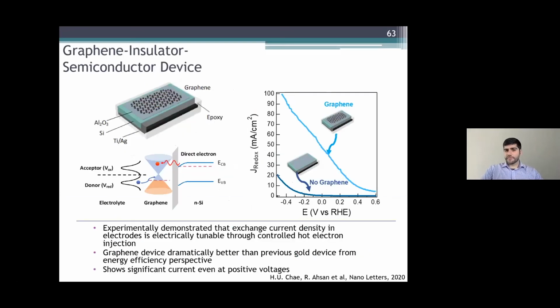And we also did this with graphene, and we found that we could again get these pretty nice shifts over to lower applied voltage for the hydrogen evolution reaction, and it was a little bit better than our gold devices. And something that was particularly interesting about the graphene is that we got a lot of modulated, what we call direct injection current, where essentially the silicon electrode was injecting electrons both into the graphene and into the solution at the same time, doing it almost through parallel channels.